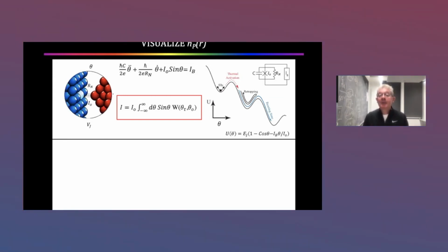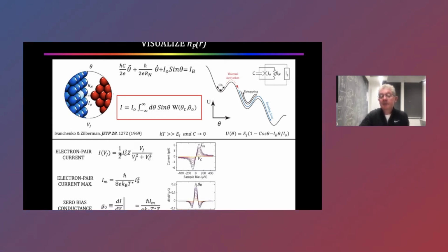He showed that even if the phase is not rigid between the tip and the sample, suppose the horizontal axis here is phase difference, and suppose the phase is wandering around in some stochastic way, as long as the average of the phase over the sign of the phase is not zero, then there is an electron pair current. And the electron pair current occurs at finite voltage. But the electron pair current has a maximum, and the maximum is in theory proportional to the Josephson critical current squared. And the electron pair conductance has a big peak at zero bias. It's not a Majorana, don't get excited. It's a peak in the pair conductance, and the magnitude of that peak is proportional to the maximum in the pair current, which is proportional to the Josephson critical current squared.